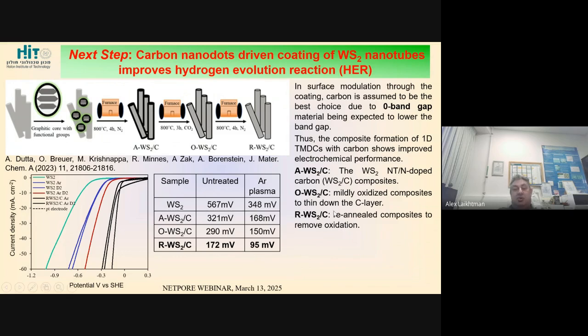So after this, there was an oxidation process to thin down the carbon layer, and then there was a reannealing to remove this oxide layer. And then we compared again the overpotential, and of course all other measurements that I'm not showing here, for differently treated samples.